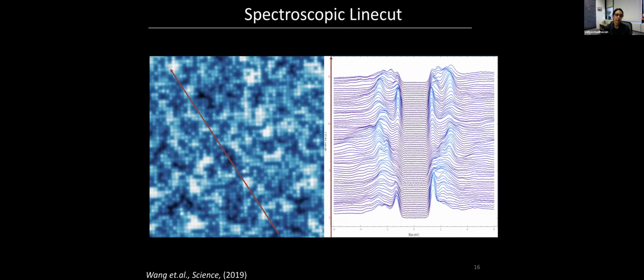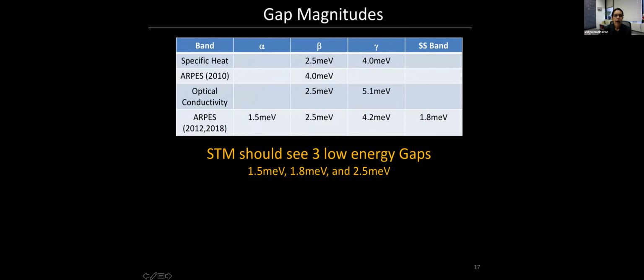And because of the quality of these crystals, what you can see very nicely when you take STM data is a beautiful superconducting gap with a very flat density of states. Now, this here is a line cut. It shows you spectra taken along this line. And what you see immediately is A, there are multiple coherence peaks, right? You can see one here, and so on. And B, these coherence peaks actually shift around as a function of position. So it's obviously electronically inhomogeneous, and there are multiple gaps. And these multiple gaps come from these various pockets that I was talking about earlier that cross the Fermi energy.